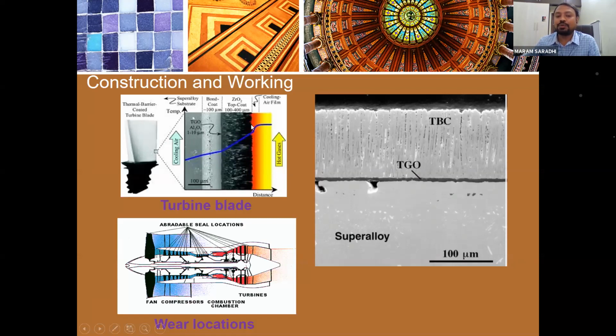Okay, when it is exposed to the temperature, for example, if you are experiencing 1400 degrees centigrade here, in the ceramic coating, the turbine blade only experiences maybe 900 to 1000 degrees. That is how you are protecting the turbine blade. If you don't protect the turbine blade, it immediately deforms in shape and it cannot perform as you expected.